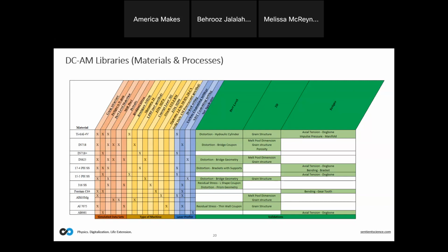So how are the effects of flaws or surface roughness accounted for in the models? Very good question. Again, the advantage of this type of damage mechanics approach is that we are not telling the solver where the bad area is, where the weak point is that the failure is going to start. Basically, all of those competing factors are already in the microstructure. In the microstructure, you might have some grain boundary mismatch, you might have inclusions, you might have porosity, and also, of course, you have the surface roughness effects. So they're all there based on their severity relative to each other, and based on the type of the loading that you're applying, and then, of course, based on the material properties, they are competing with each other.